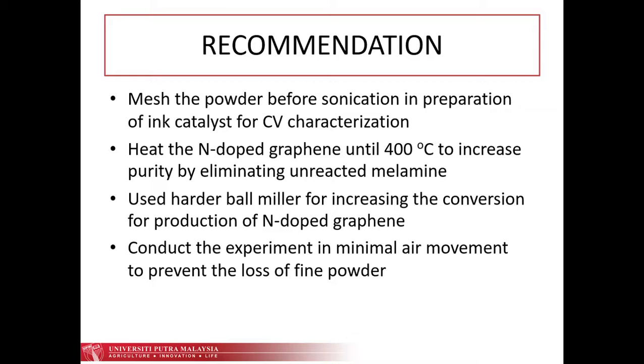First is to mesh the powder before the sonication in preparation of the ink catalyst for characterization. This is shown in the result of the CV, where sample 4 has a better ORR value compared to sample 3, because sample 4 is finer due to using a small ball size. Therefore, the absorption of the ink on the glassy carbon electrode is also better, which gives a more sensitive result. So it's recommended to mesh the powder before we sonicate.